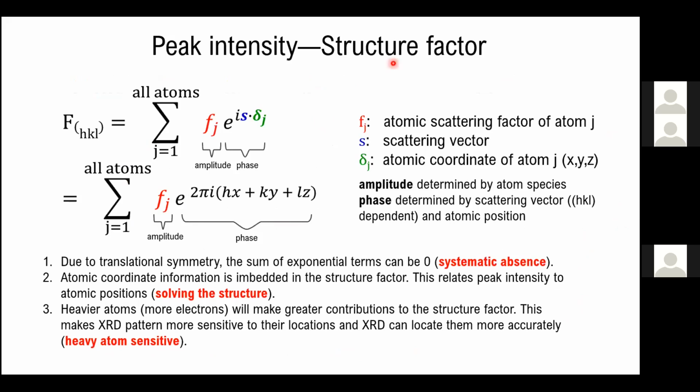So the first one is the structure factor. I think I mentioned this term several times already. I just want you to have a deep impression about this structure factor. It's really, really important, and we really need to understand it. To put it simply, it's summarizing the contribution from all the atoms in the unit cell, which is expressed by this term. And as we see here, each atom is contributing one part, which is amplitude. The other part is the phase.